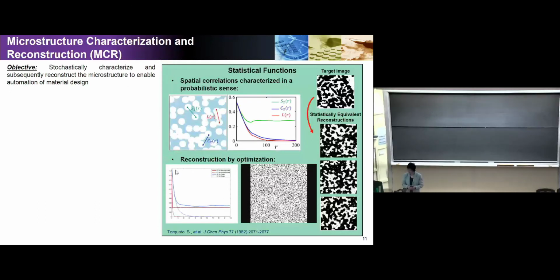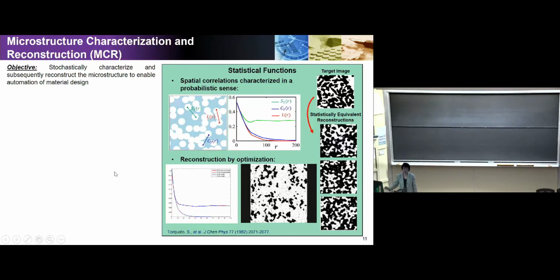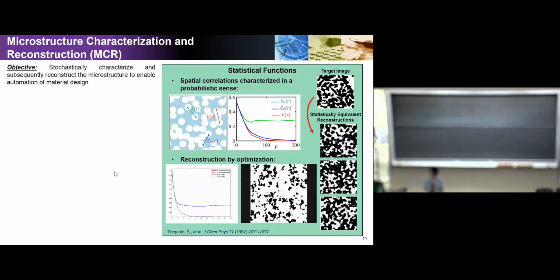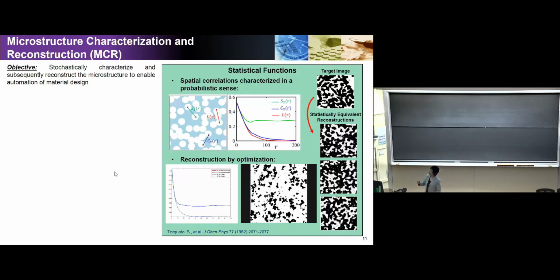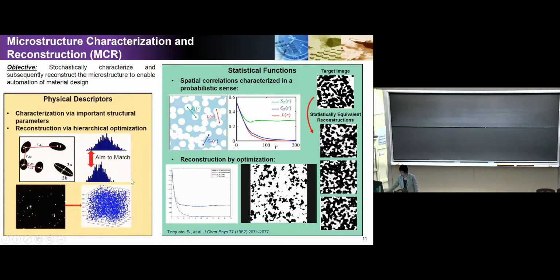The most original method is from a person called Torquato at Princeton. He wrote a book and he also has papers on this method called the correlation function. It uses statistical functions to fully represent the microstructure morphology. And this kind of reconstruction method is very expensive. It's an optimization-based approach. Basically, you start by randomly placing the particles and then try to optimize them so the correlation function matches the target correlation. So it's very expensive. You cannot really use it in the design process.